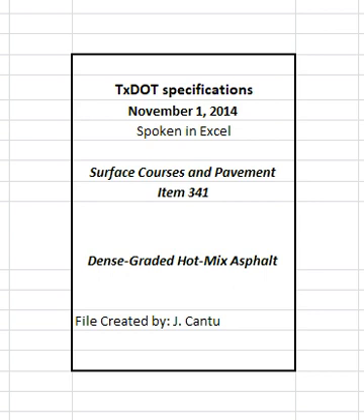impurities. Supply intermediate aggregate from coarse aggregate sources, when used, that meet the requirements shown in Table 1 unless otherwise approved. Test the stockpile if 10% or more of the stockpile is retained on the number 4 sieve, and verify that it meets the requirements in Table 1 for crushed face count, TEX 460A, and flat and elongated particles, TEX 280F.